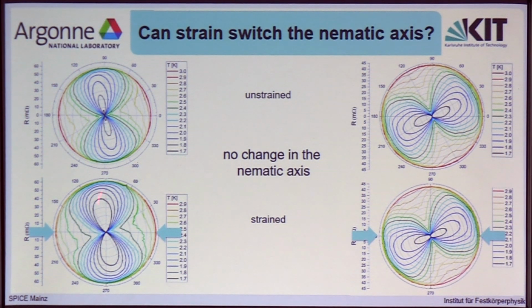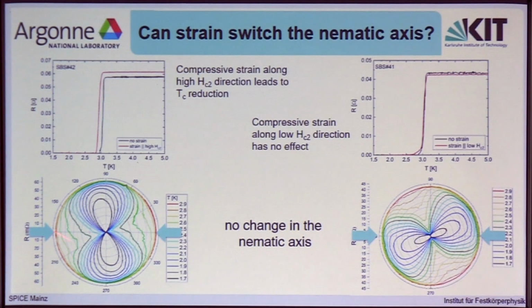And of course, we could ask ourselves now whether we are actually applying strain. Are we straining our sample? And I think the answer is yes, because we've also measured the transition temperature, and you can see a clear reduction of the transition temperature, at least for this one sample.